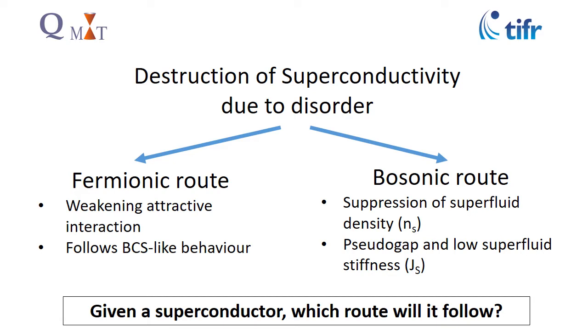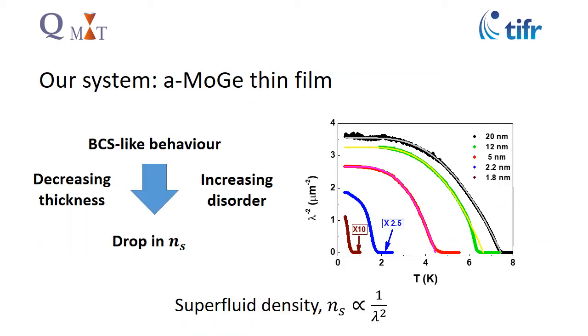To investigate it further, we took one superconductor which has been extensively studied to show the fermionic route, which is the amorphous molybdenum germanium thin film. As you can see, it was grown by the pulsed laser deposition technique, and we tuned the disorder by decreasing the thickness. The measurements we have done are penetration depth measurements, scanning tunneling spectroscopy, and magnetotransport measurements.